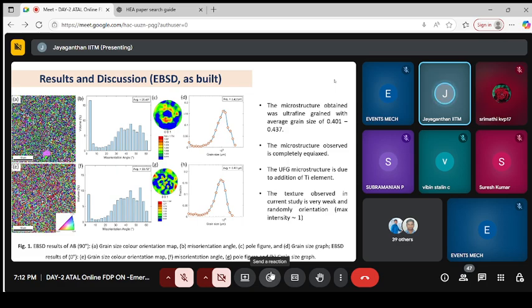You can see at the bottommost, EBSD is nothing but electron backscatter diffraction. We look at the vertically built sample and the horizontally built sample. Figure A represents the grain size color orientation map. A represents that each grain has its own orientation. That's why we want to quantify how many grains are with a particular orientation. Figure B gives the misorientation angle. C is the pole figure. Again, we want to visualize using the pole figure.